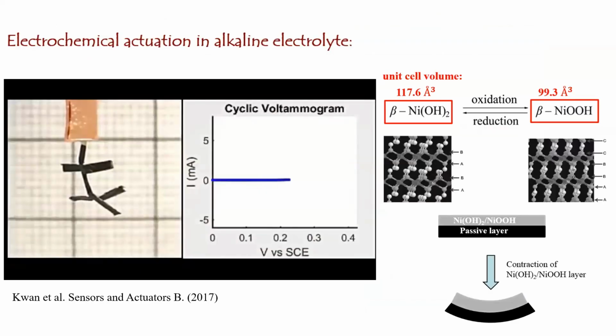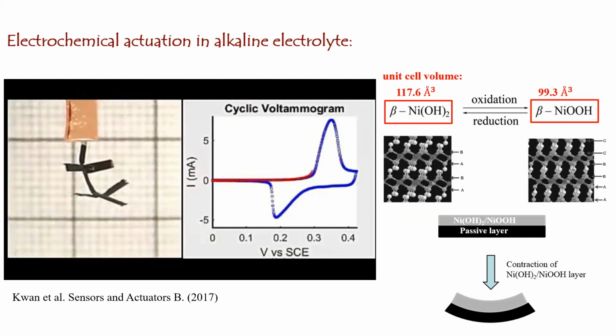So I said that there are 2 mechanisms. The one that you have seen just now was the electrochemical actuation. To prove that this is really some redox reaction driving the motion, we now deliberately slow down the signal. So this is the type of material that would exhibit this oxidation and reduction. When the material is oxidized, the unit cell volume of the material actually decreases, as you can see from the red number at the top. So when the voltage now enters into the oxidation, the material shrinks.